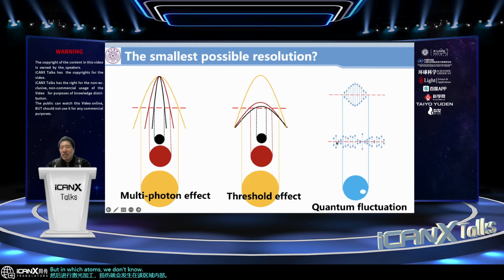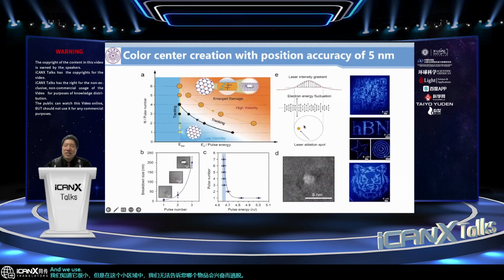It's random. So it means we have already improved the spatial resolution from the conventional optical diffraction limit to the quantum limit. We know it's small, but in this small area, we cannot tell which atom will be excited and escape from the system. Using such an effect, we can produce this kind of very small single atom damage. We measure the damage area size to be smaller than 5 nanometers. It means we know the damage is within such a small range, but we don't know whether it's at the center or at the surrounding region. But anyway, it's already close to atom level fabrication.